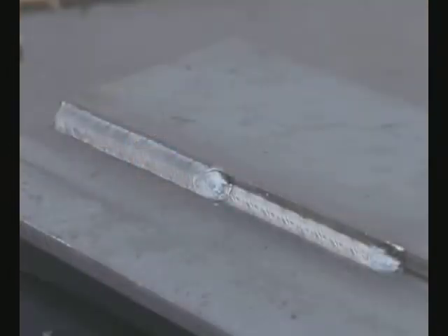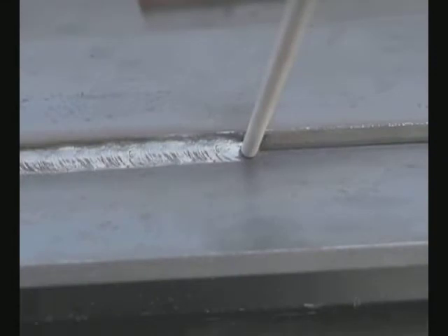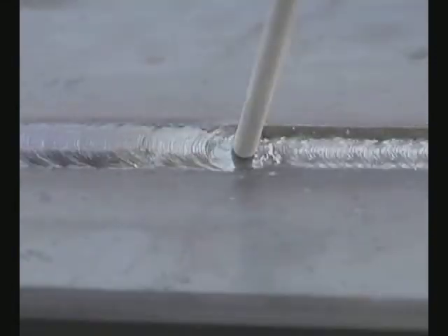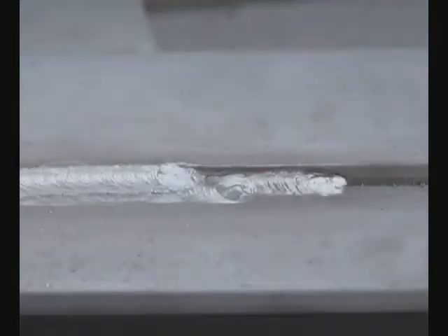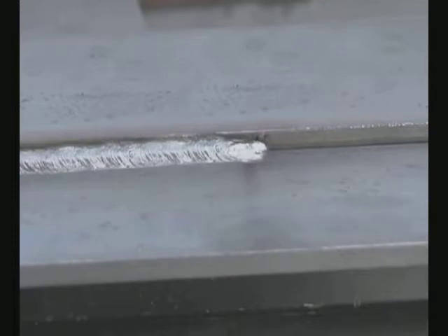Because the filler metal remains fluid longer, try running straight without any rod movement, keeping the arc on the leading edge of the puddle. On thicker metal, you may not be able to make a full fillet in one pass. You might be able to get it in two passes. The first one smaller and flat, then slowing down to carry more metal and crown the bead on the second pass. It might take 3 or more passes, and on heavy welds, use 7018 to prevent the bottom beads from cracking. Put the first one in fusing the bottom corner.